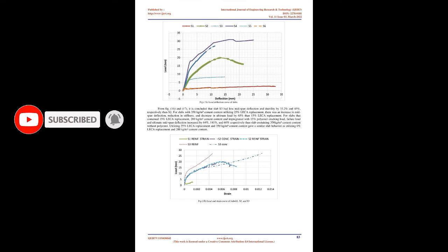The impact of polyester was 66% improvement in the indirect tensile strength, but it was 355% in the presence of LECA, as illustrated in Fig. 13. Flexural strength of mix 1 increased by 3.5 times when polyester was added, but it increased by 36% in the presence of LECA and polyester, as demonstrated in Fig. 14.